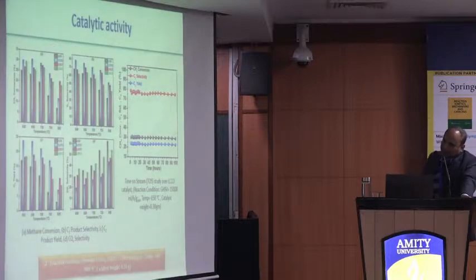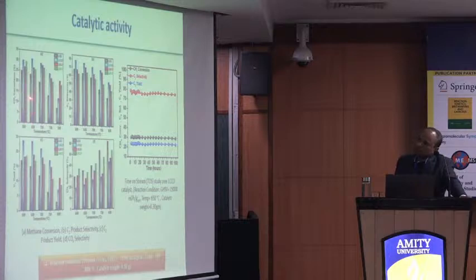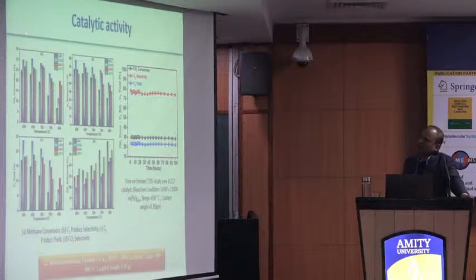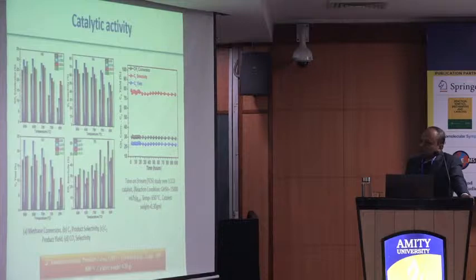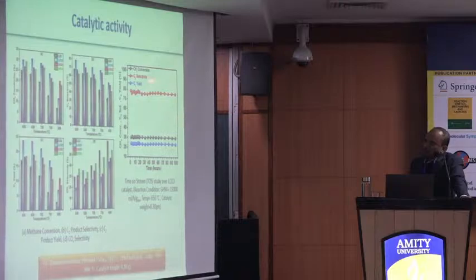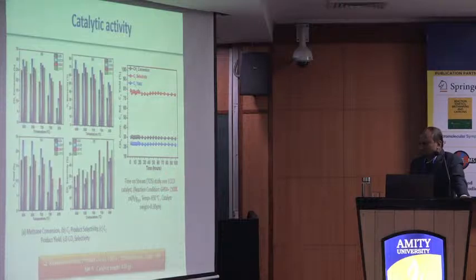And this is the catalytic activity study. We have done the reaction between 600 and 800 degrees, and we found that 650 degrees is showing the optimum conversion and selectivity. When going to a higher temperature, we are getting more CO and CO2. We have also done this reaction for 100 hours, and we can see that the catalyst is stable even after 100 hours. This is the typical reaction condition. We are using 15,000 space velocity, which is very good, and normally we are using 0.3 gram catalyst for all the reactions.